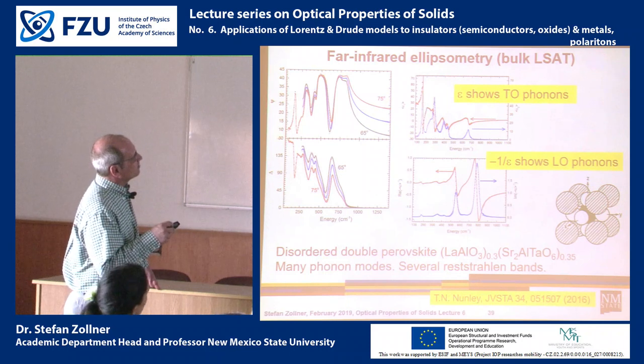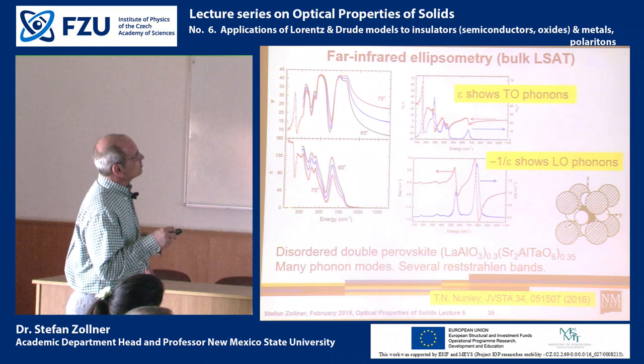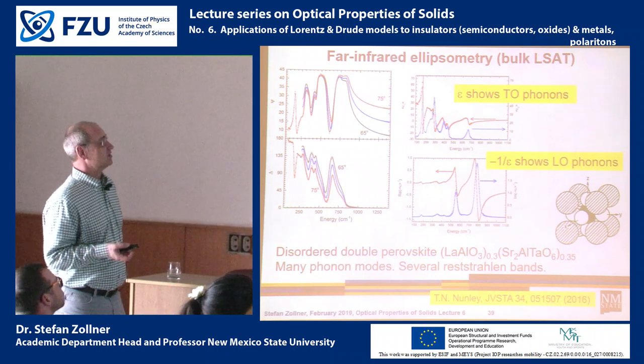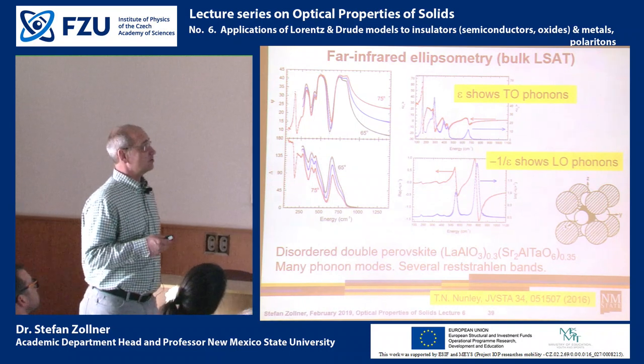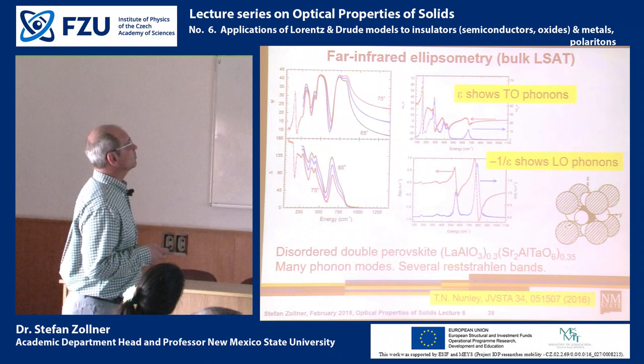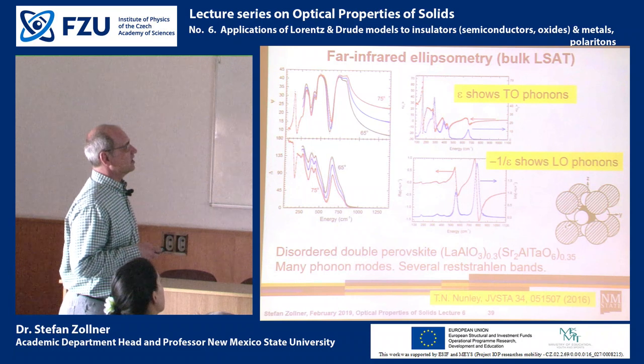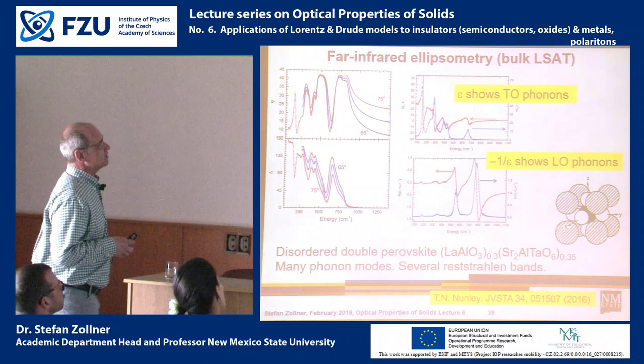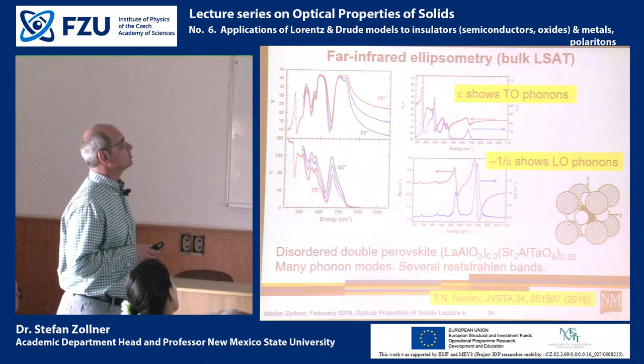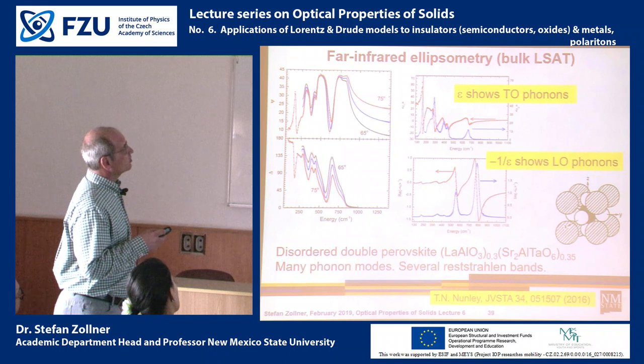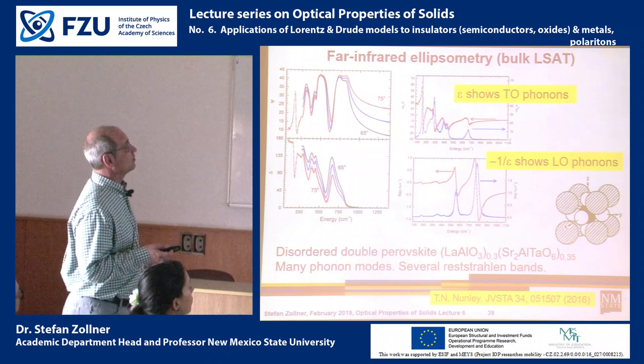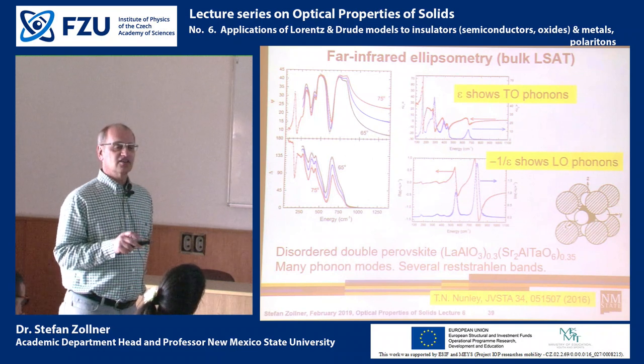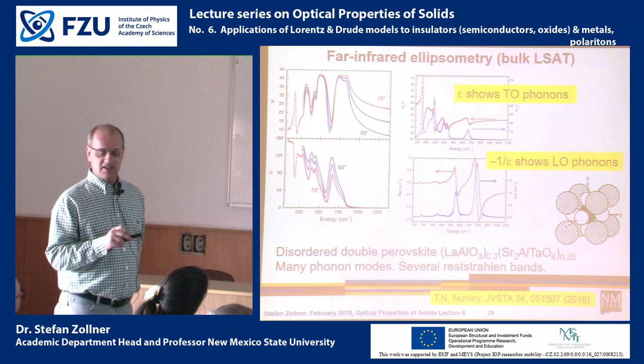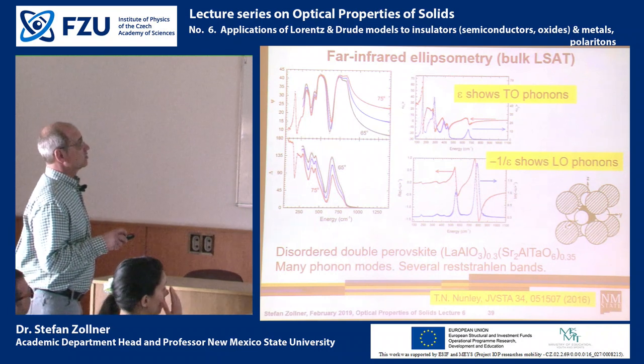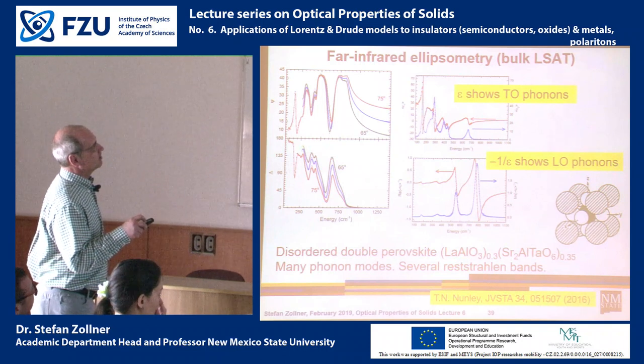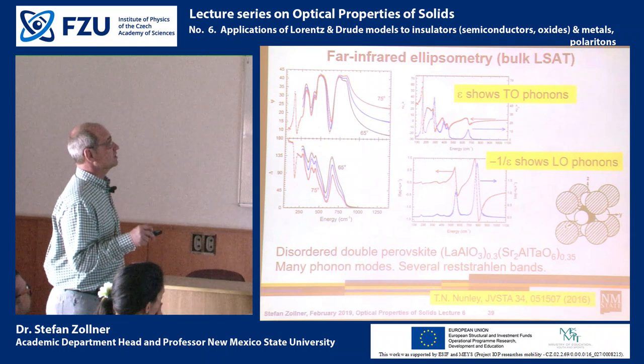You will see that in the spectra, we can go down to around 50 wave numbers. So there are ellipsometers that can measure down to 50 wave numbers. I've already mentioned the one which is in Brno in Josef Humlicek's lab. These measurements were done by Premysl Marsik, who is in Christian Bernhard's group in Fribourg in Switzerland. So it is possible to measure at lower frequencies if there are phonons which have a resonance frequency lower than the one that can be measured on the instrument in this facility. The commercial instruments only go down to about 250, but some people have built their own instruments that can go to lower frequencies.